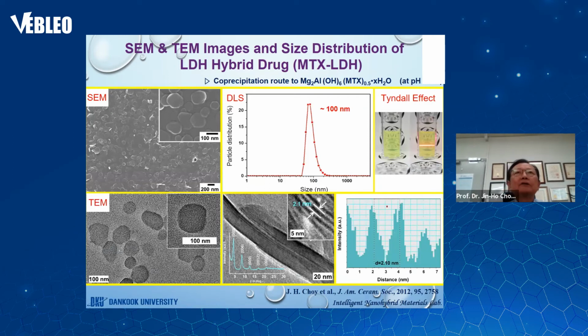According to the X-ray diffraction analysis of the prepared MTX-LDH, the basal spacing of LDH was expanded from 7.7 angstrom to 21 angstrom upon encapsulation of MTX into the LDH layer. As you can see in the SEM image on the left-hand side, the average particle size of MTX-LDH was determined to be approximately 100 nanometers, which is in good agreement with the particle size distribution results obtained from Zetasizer. The cross-sectional high-resolution TEM images of MTX-LDH clearly show a well-ordered layer structure. The interlayer distance between periodic lattice fringes from the 00L planes was approximately 21 angstrom, which is in excellent agreement with the XRD results, as you can see here in the middle of this figure.